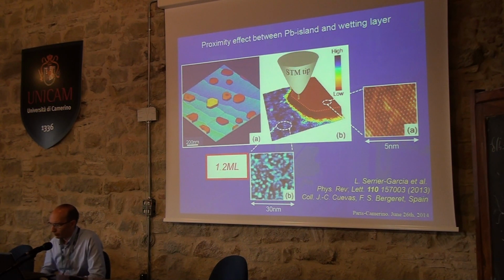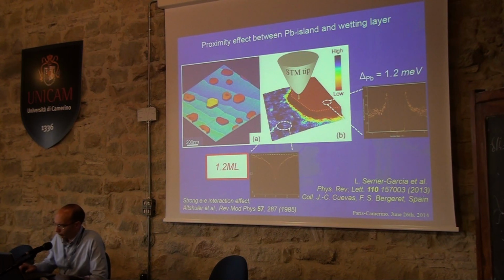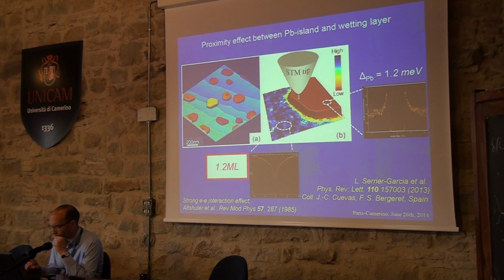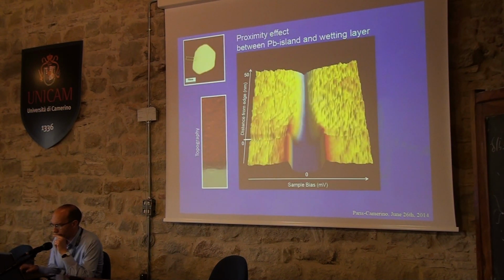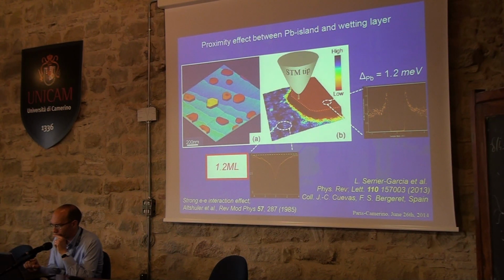On the next slide you see that the islands are indeed superconducting. They are characterized clearly by a superconducting gap, which is about 1.2 millivolt. Very nice BCS gap. But if you go to probe the amorphous wetting layer, you will see a sort of zero bias anomaly with no superconducting coherence peaks. This anomaly is a well-known anomaly of Altshuler-Aronov, which is related to electronic correlations in this diffusive and disordered medium.